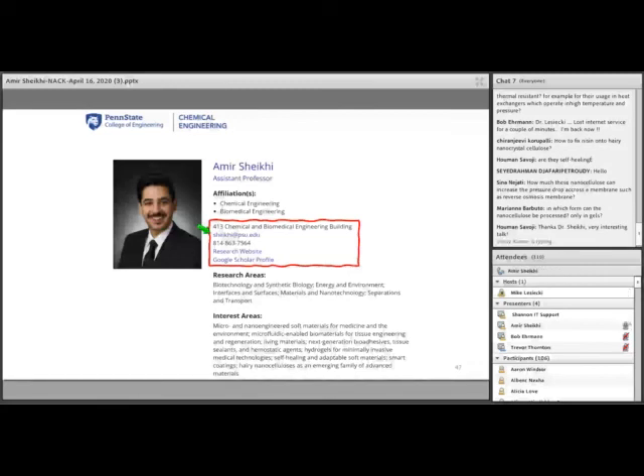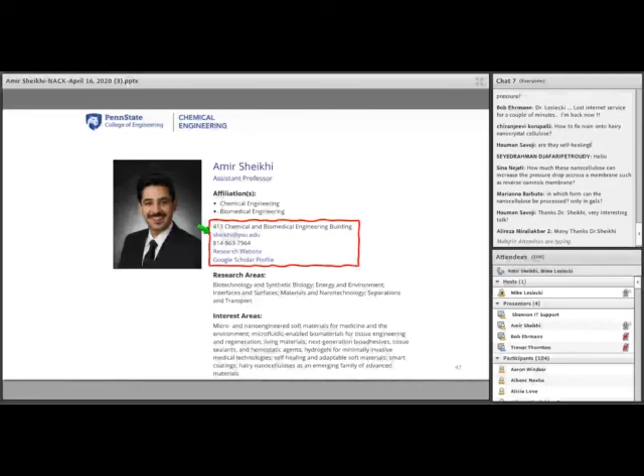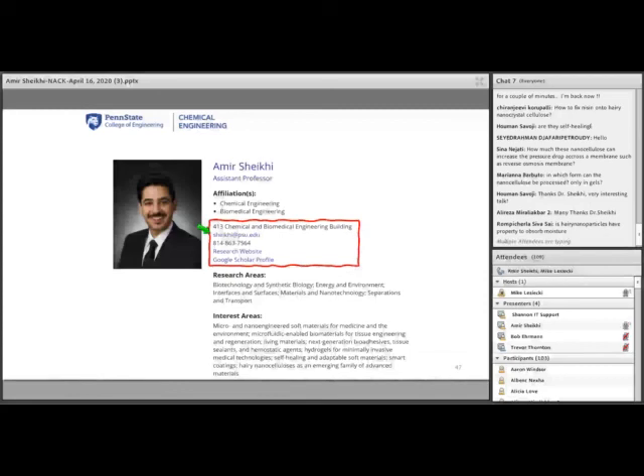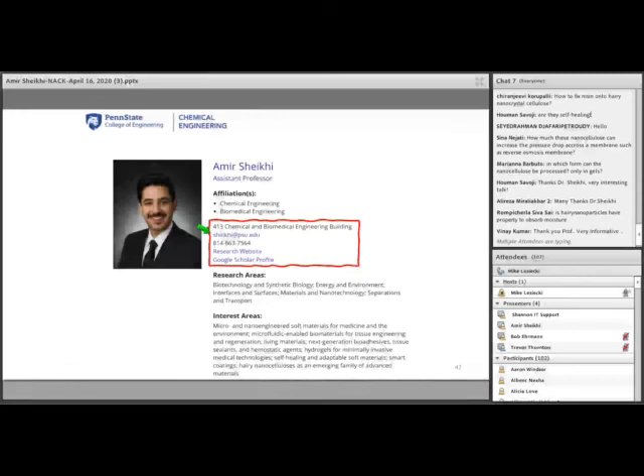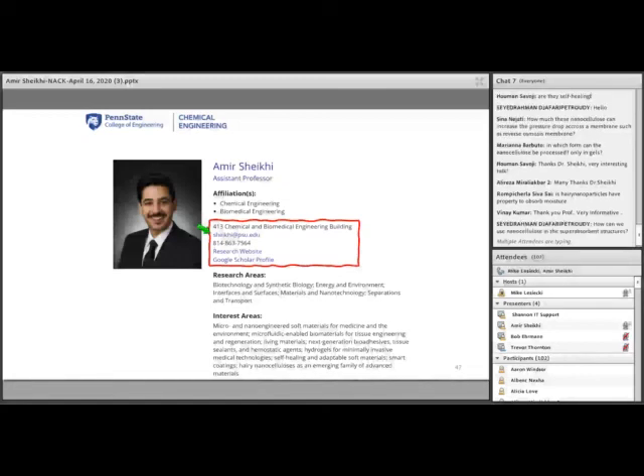So, hairy nanoparticles can be produced in different forms. We can have anionic versions of that with carboxylic acid groups or other types of anionic groups, neutral versions of that with aldehyde groups, and positively charged versions of that with, for example, amine groups. So depending on the chemistry of the surface, we can think about chemical conjugation of these nanoparticles with the functional groups on the surface. For example, if we have a surface that has, let's say, amine groups, and we want to readily functionalize it with hairy nanoparticles, simply using aldehyde functionalized nanoparticles will result in a Schiff-base reaction between these hairy nanoparticles and the surface, and conjugating them to the surface.